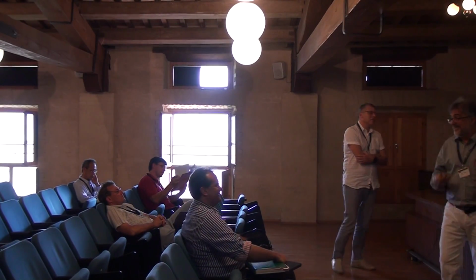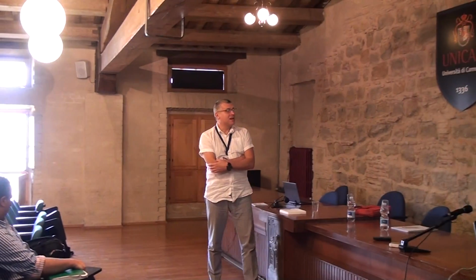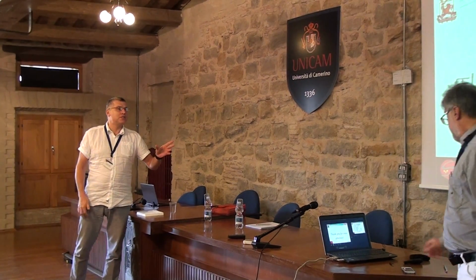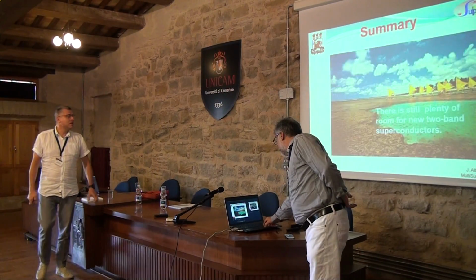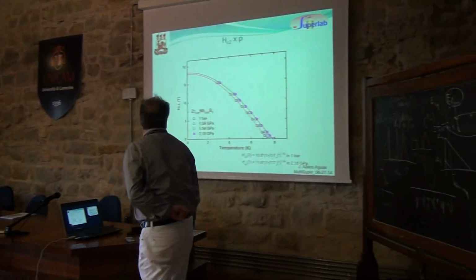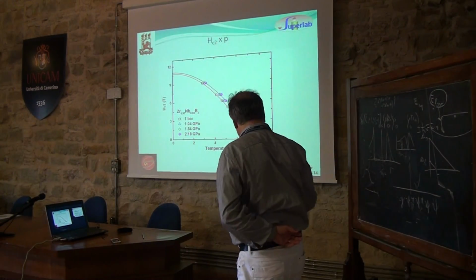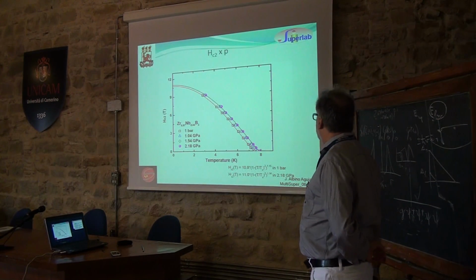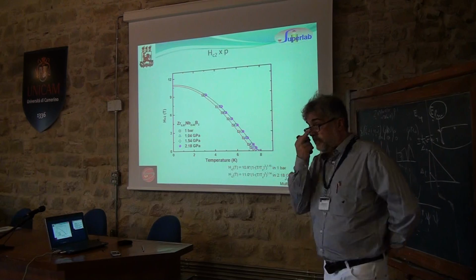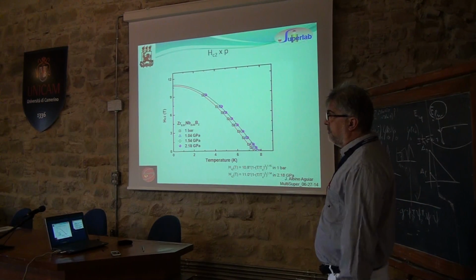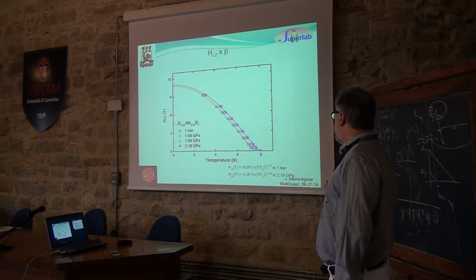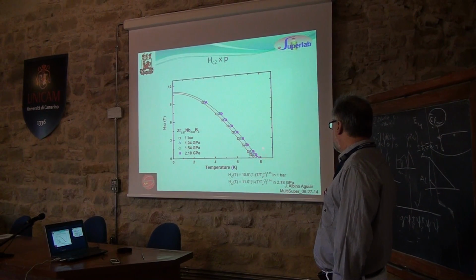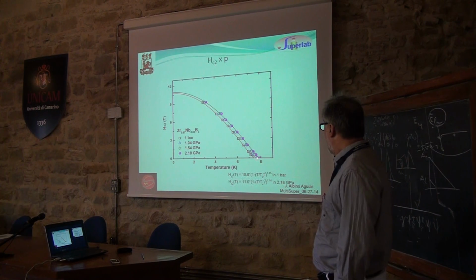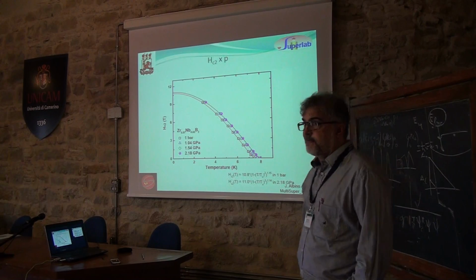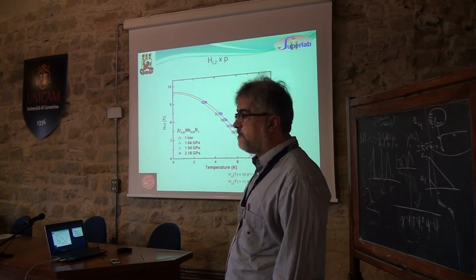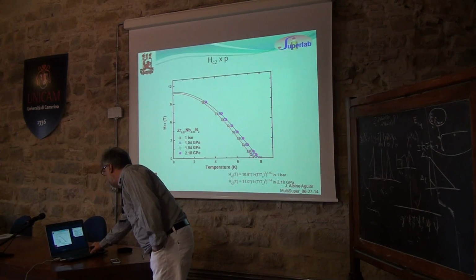Nobody. Neither do I. I have a comment. Albino, can you show the HC2 behavior? Yes, this figure. You see that, in fact, for me, it's no doubt that this is a multi-band superconductor because HC2 has these features close to TC. So this fit is just a guide, nothing more. If you start to fit data which are close to the TC, the line will go much lower. So to fit this data, you need to introduce extra terms. It means that this is not the case in the usual BCS, one-band superconductor.